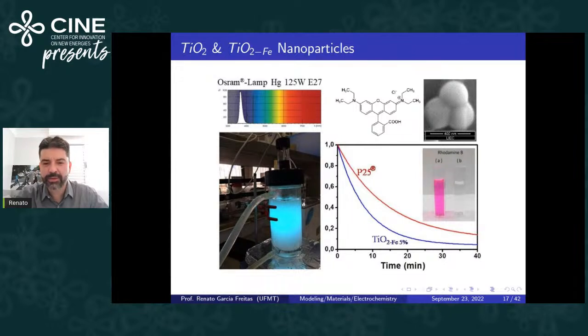No, but this one with doping around 5% with iron. Yeah, and you obtain the activity for the kinetics of degradation of rhodamine. In this case, for example, it is massive. I don't remember how many orders of magnitude the increase of the degradation the authors obtained for titanium dioxide iron doping here compared to P25. And we have the Degussa. That's the main titanium nanoparticle used in the industry, isn't it?